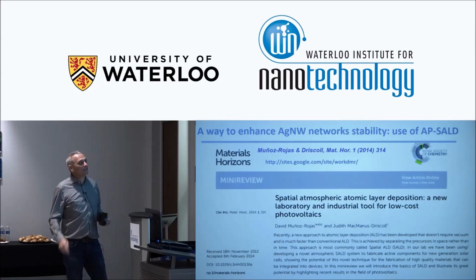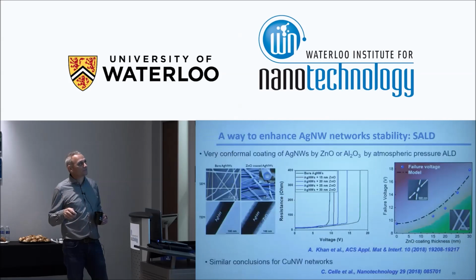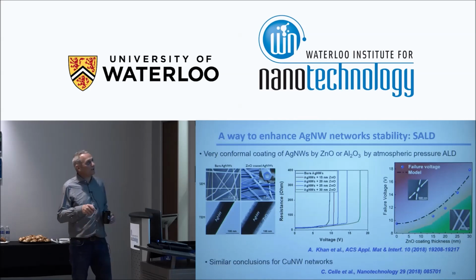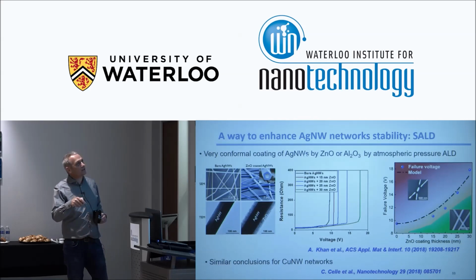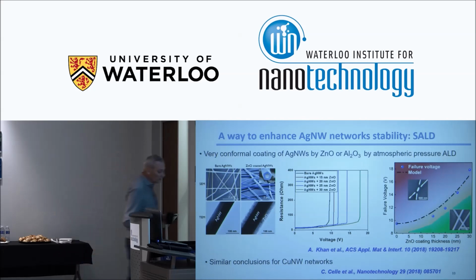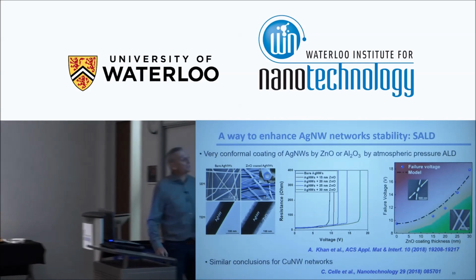But there's a growing, interesting field around atmospheric pressure spatial atomic layer deposition. What we did was deposit conformally, let's say, zinc oxide or alumina around silver nanowires. This is bare nanowires, and this is coated nanowires, observed with SEM or TEM. So again, it's the same TEM picture as before. And when we coat them, we can coat them with a conformal layer of zinc oxide with a thickness of a few tens of nanometers.